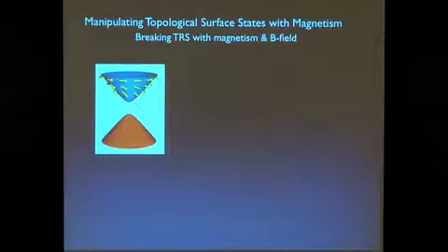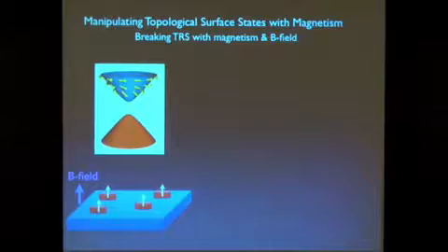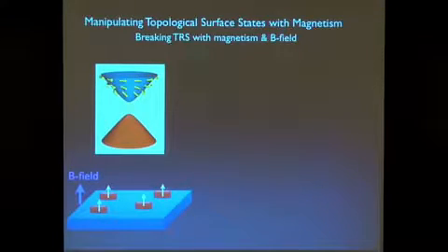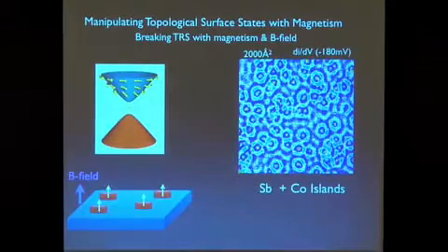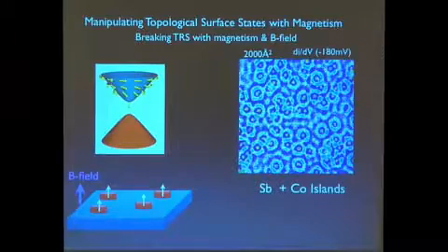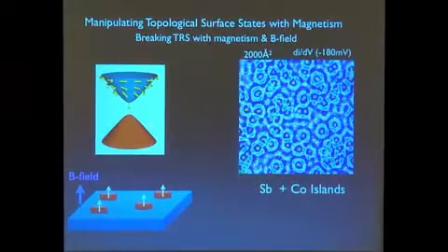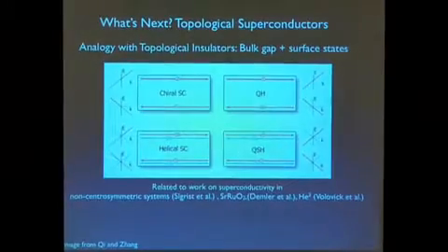I sort of covered a lot of material here having to do with the protectedness of these topological surface states. So one thing you can do is try to control this protectedness. The way you can do that, for example, is by introducing time reversal symmetry breaking with magnetic impurities. Or the experiment that's going on right now in the lab is to put islands of magnetic material on the surface and manipulate the spin orientation of this island with a magnetic field to break the symmetry, introduce backscattering, which will also gap these topological surface states. So there would be a way in which you can manipulate these surface states if you can break time reversal symmetry using magnetic perturbation.